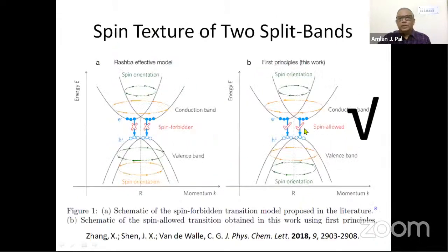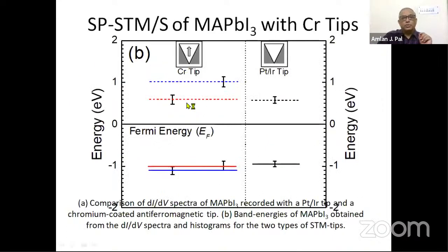This means that this model is actually valid. So it is a spin allowed transition model, so recombination should be possible. Then we talked about the domain, because we got two types of states. So why did we see these two types?